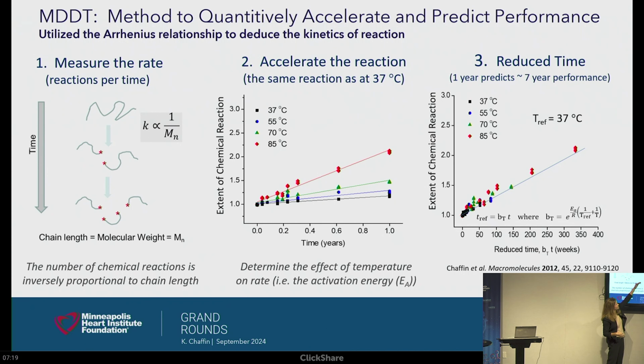And if you create this series of curves, you can then use the Arrhenius equation to manipulate those curves and make a reduced time plot. And what I want to point out here is you can see the black data is at 37. We could have either extrapolated the black data. That's dangerous business as we go 15x, 30x. But we can use the higher temperature data to make sure that extrapolation is for sure linear, okay? So that's what we've done.